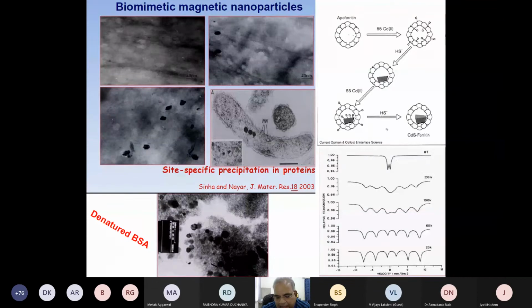In the next experiment, while making this protein solution, we dissolved ferrous and ferric ion into it and then raised the pH a little bit and allowed it to be there for a week. After a week, once we saw it in the electron microscope, we noticed that there is a nucleation of a black particle. You can see it's in the black color. A black particle inside the cavity of this gel. And we were lucky that we got the next location. There was this cavity fully occupied by a similar crystal. And the shape and size, you can see it's very similar to the cavity that we have seen in our first picture. And we have seen even on the same sample at other places, we have got a number of such crystallizations in those cavities. There was no crystallization in the bulk.